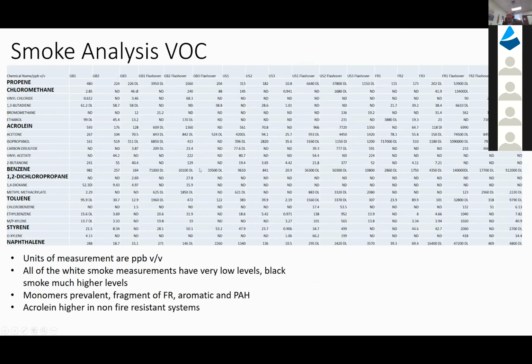We did a lot of other analyses. We looked at volatile organic compounds. I'm not going to go through all of this because it's an eye chart, but you can see that the highlighted ones, the bolded chemicals, radically differ from the UK rooms to the French and the US rooms. You see a lot lower production of the very toxic chemicals in the GB room pre-flashover, and that's a lot longer period of time to escape. So your exposure to the smoke is somewhat limited, and as a result, you're not going to have near the severe health effects you would for both the French and the US rooms.